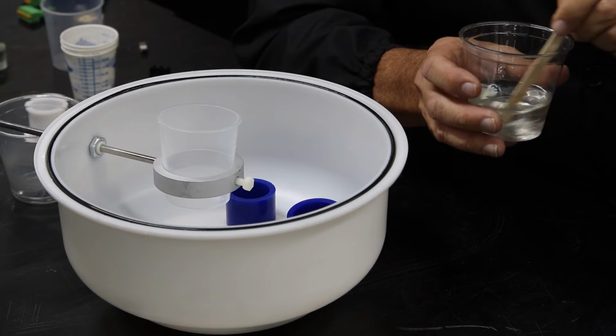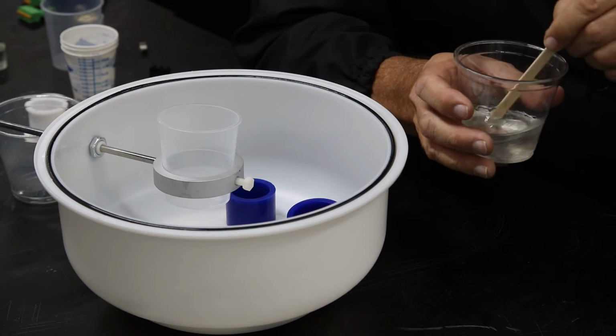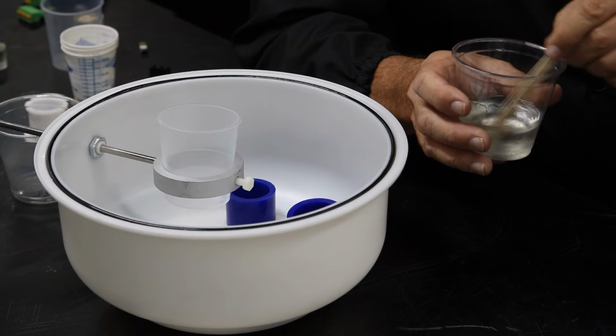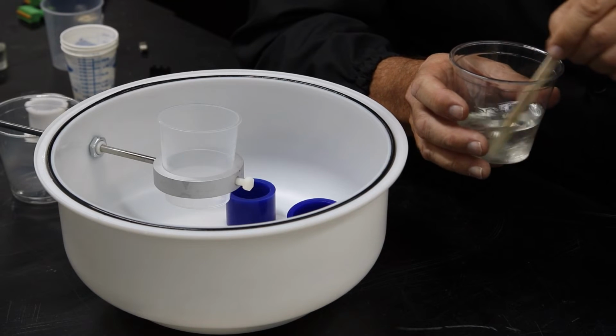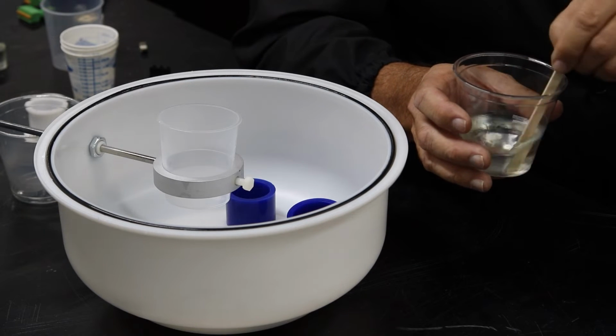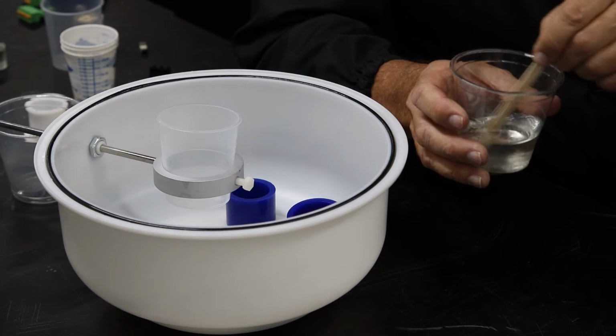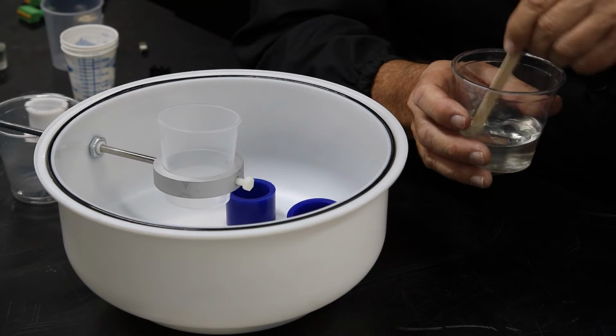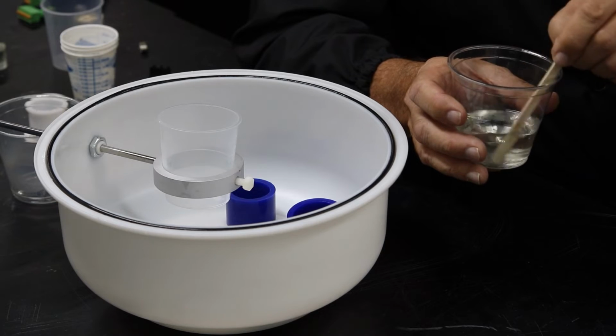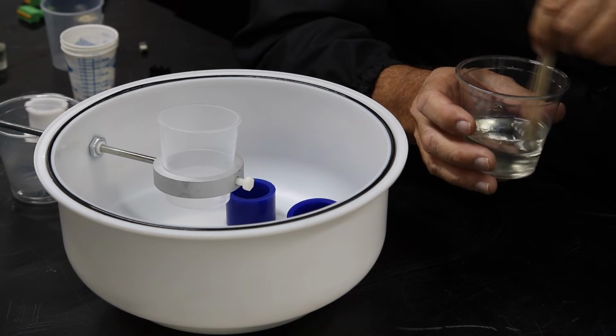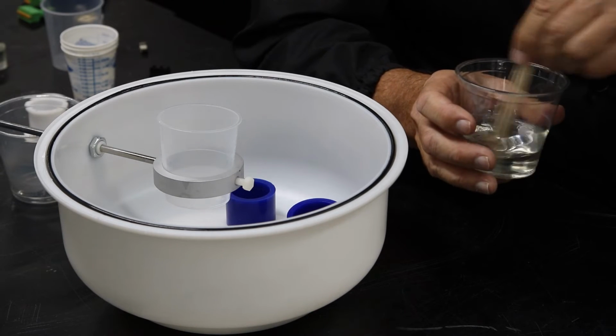So what you want to do is make sure that the liquid turns from cloudy to clear. And then just for extra measure, go a few more seconds after that. This will make sure that you've got a homogeneous solution so that when it's curing, you don't get spots that are partially cured and some that aren't. So I think we're pretty good here.